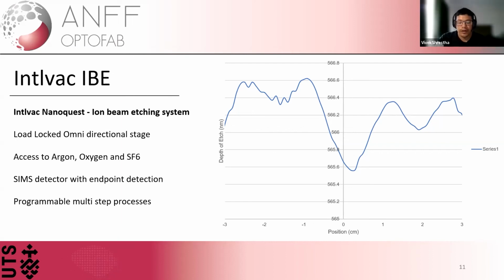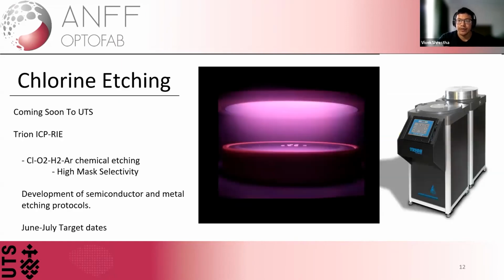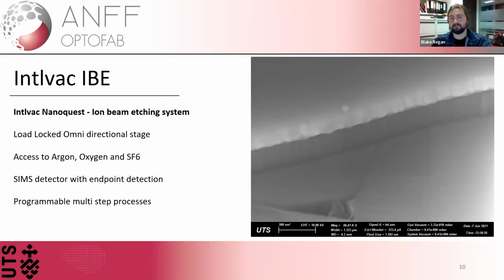Yeah, on the next slide, Blake, was that a diamond? Like with the silicon dioxide? Yeah, this one. Yep, that's silicon dioxide, and the material that I etched is diamond. This is using a very low power oxygen etch onto the surface, which meant that the selectivity against the silicon dioxide was fantastic. So we've been in the process of developing nanofabrication techniques using HSQ as an etch mask. So HSQ under EBL becomes SiO2, for those of you who aren't familiar with EBL processes. And so when you create that structure, we can then go down and create any sort of structure that's appropriate for HSQ. HSQ has approximately, depending on how good your SEM or your EBL system is, should be able to make structures of about 100 nanometers if it's your average day.